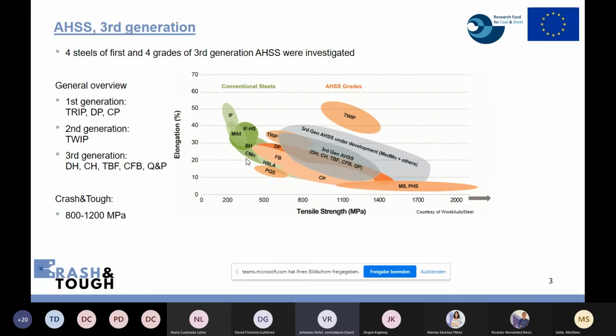Well, in the project, we investigated 4 steels of the first generation and 4 grades of the third generation AHSS. This figure gives you an overview regarding the placement of the first, second, and third generation in the so-called steel banana. In the first generation, we have the TRIP steels with very high elongation values, followed by the dual phase grades. Then we have the complex phase grades in the first generation, which show the highest strength levels but lower elongation values. In the second generation AHSS, we have the TWIP steels, which show very high elongation values, and between